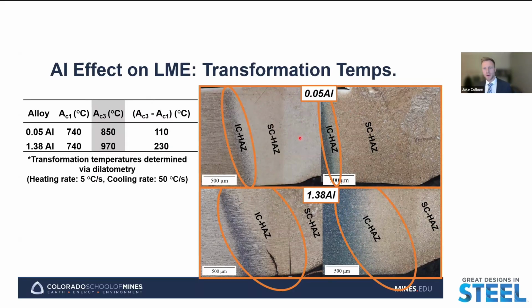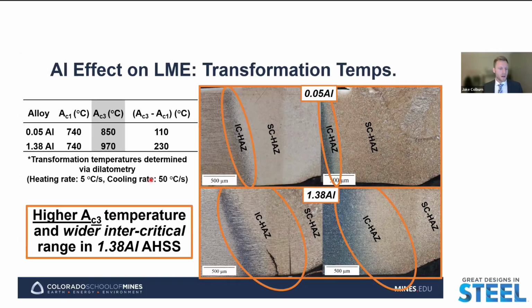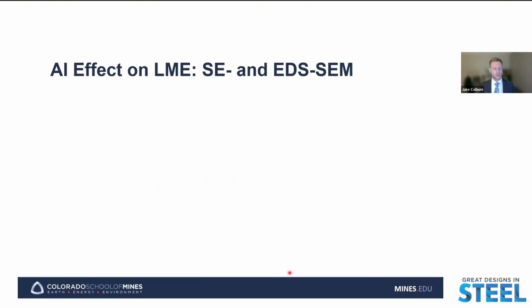And then if we take a look at the supercritical heat affected zone, we see that that region extends to much greater distances into the weld periphery for the low aluminum alloy than we see for the high aluminum alloy, where potentially this supercritical heat affected zone is not extending at all into the weld shoulder and the weld periphery. And so then the question is, why does it matter if we have an intercritical or a supercritical heat affected zone at these LME susceptible regions?